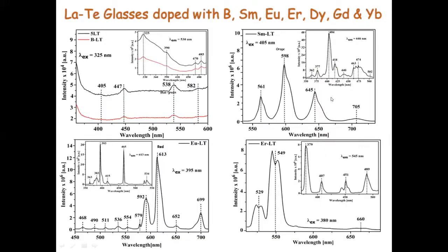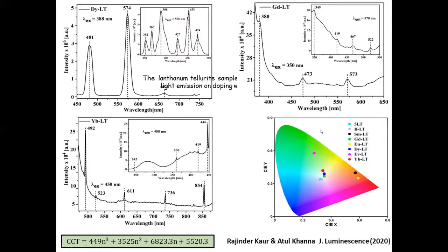Lanthanum tellurides also form glass and anti-glass phases, and they form glass ceramics, and you can introduce large concentrations of rare earth ions in the lanthanum telluride system. And some of the lanthanum tellurides, like lanthanum telluride doped with gadolinium and lanthanum telluride doped with ytterbium, are white light sources. So very good white light emission is seen.